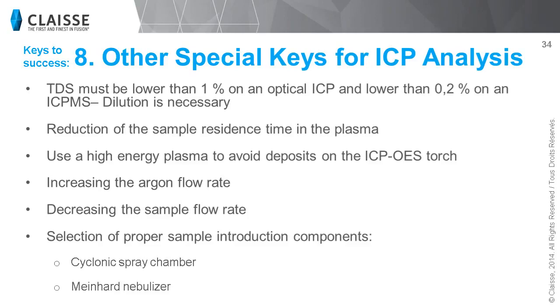By experiment in our lab, we found that the two best components to use are a cyclonic spray chamber and a Meinhard nebulizer.